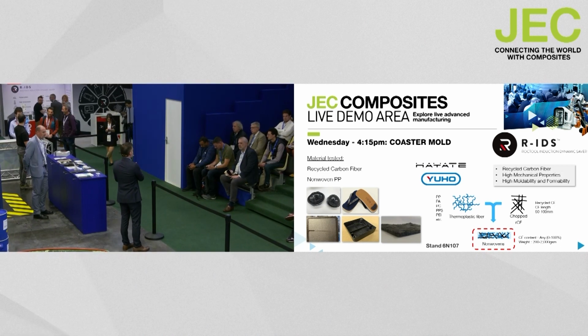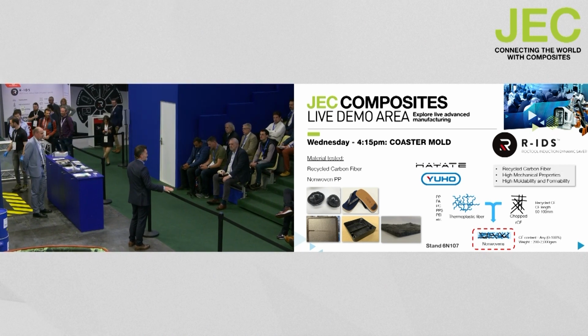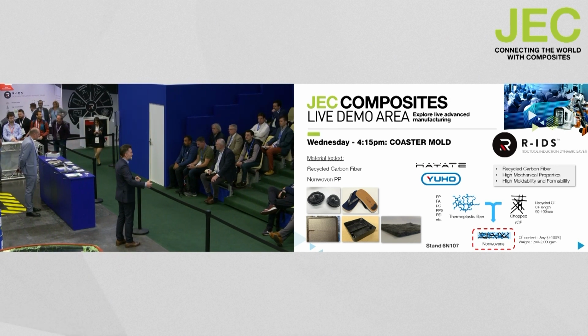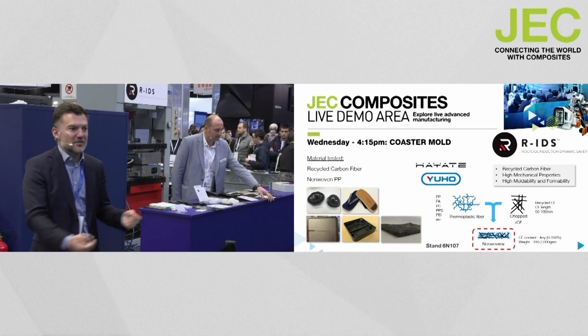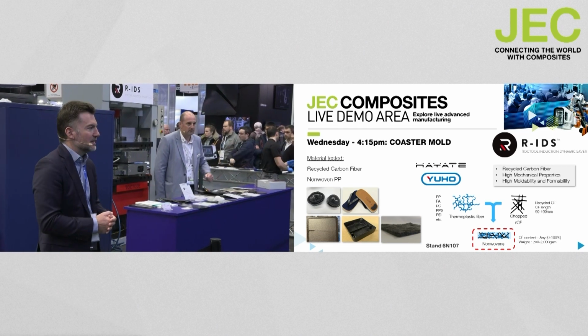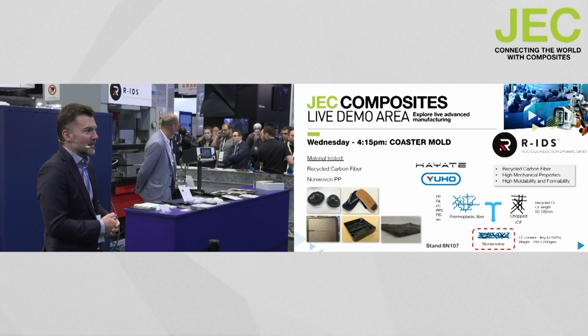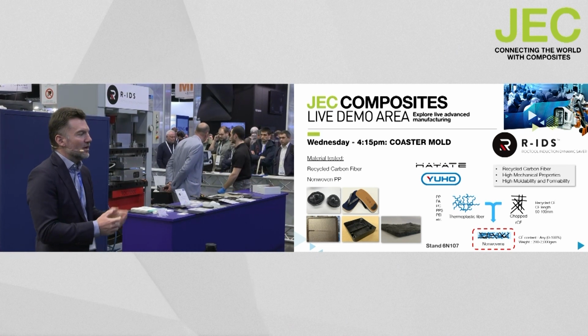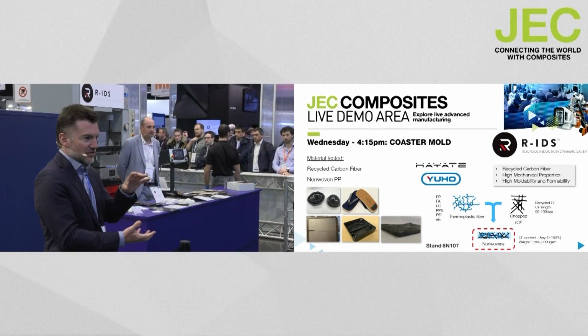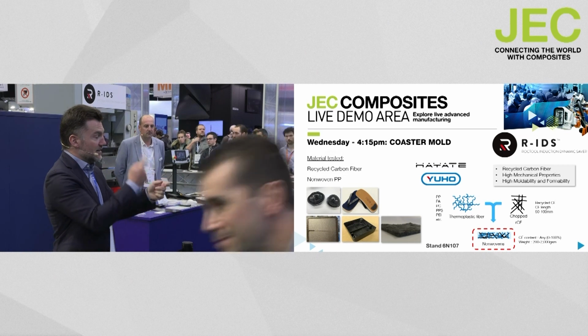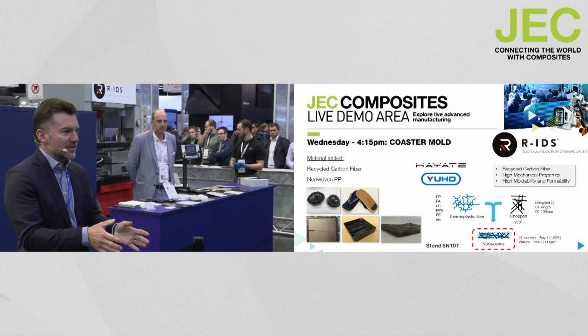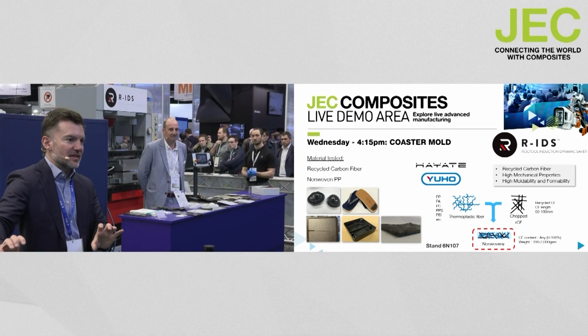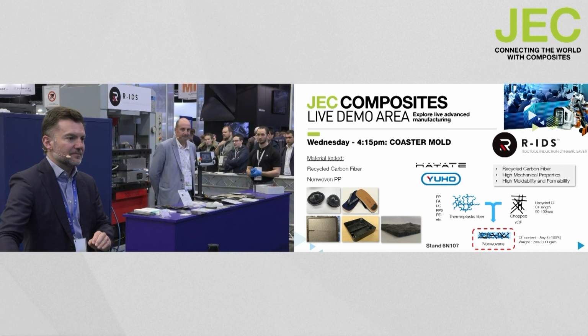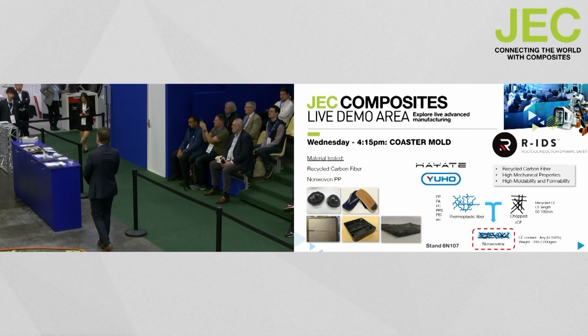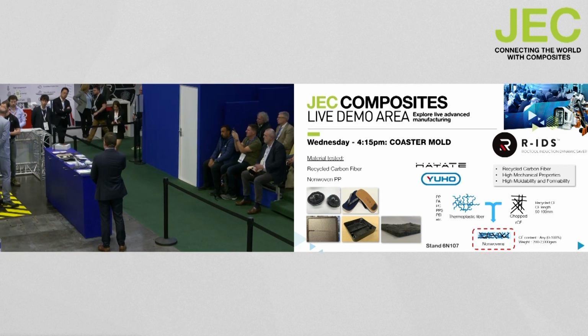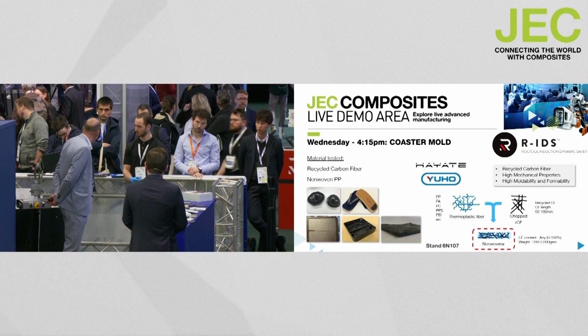And that's what we show here, because every time we start a demonstration, we start from zero. There's no preheating, there's no oven with transfer of material, or I don't know what other heating system. So 100 kilowatts to heat both sides, 50 kilowatts, 50 kilowatts. And then once you're done with that, only 5 to 10 kilowatts to keep hot and to maintain the platen at a lower temperature. So now, after 2 minutes and 50 seconds, we reach 240 degrees.